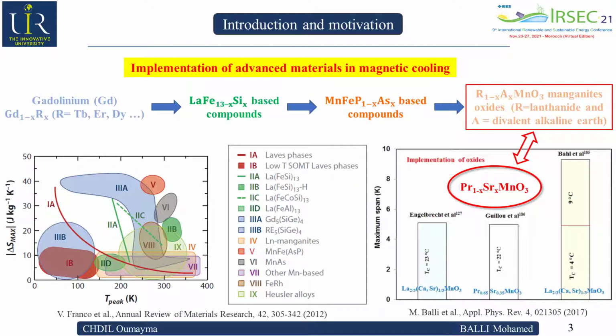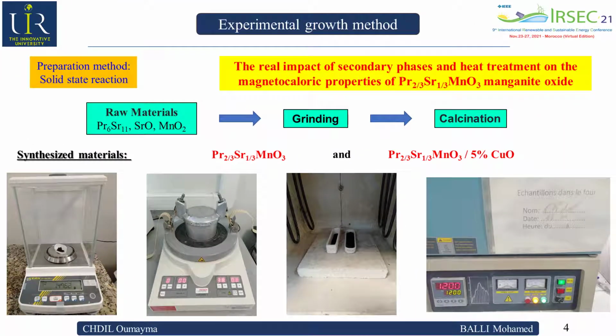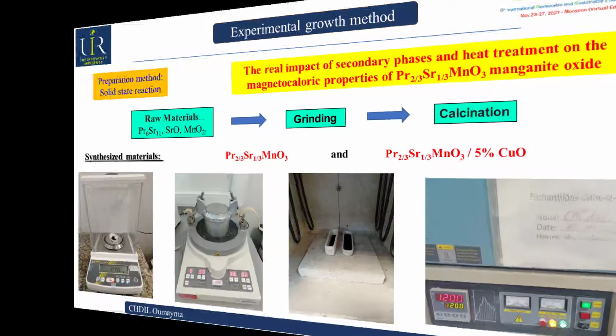As a result, our experimental work is focused especially on the Pr1-xSrxMnO3 manganite type, which exhibits a Curie transition near ambient temperature. The polycrystalline samples were prepared using the solid-state reaction method. Then a quantity of the calcined powder was employed in the composite preparation, where an amount of copper oxide was added and mixed well, and then the mixture was calcined at 1200 degrees Celsius for 2 hours.